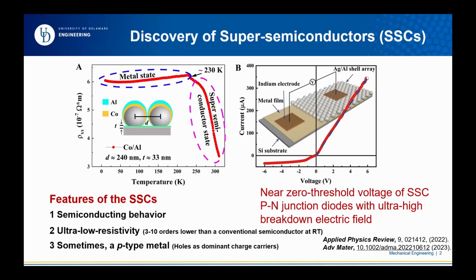This work was published just 1.5 years ago. When we use this method, the only difference is that here we use cobalt aluminum, and here we change cobalt to silver. We found this diode behavior, of course, and at the same time the threshold voltage has become very, very small compared to traditional ones, like silicon, which is 0.6 to 0.7 volts.